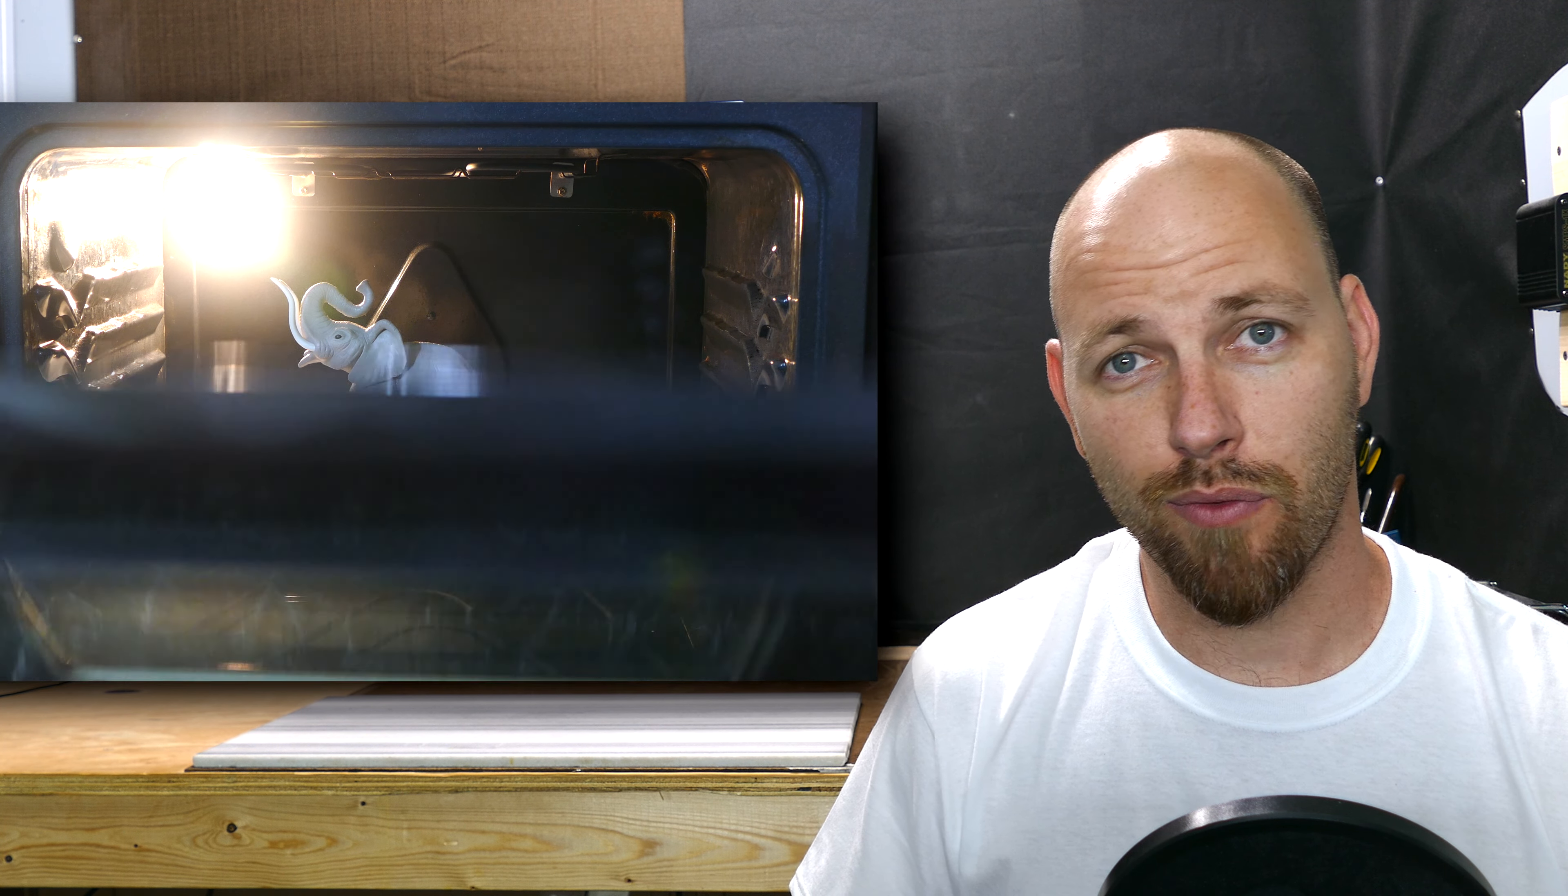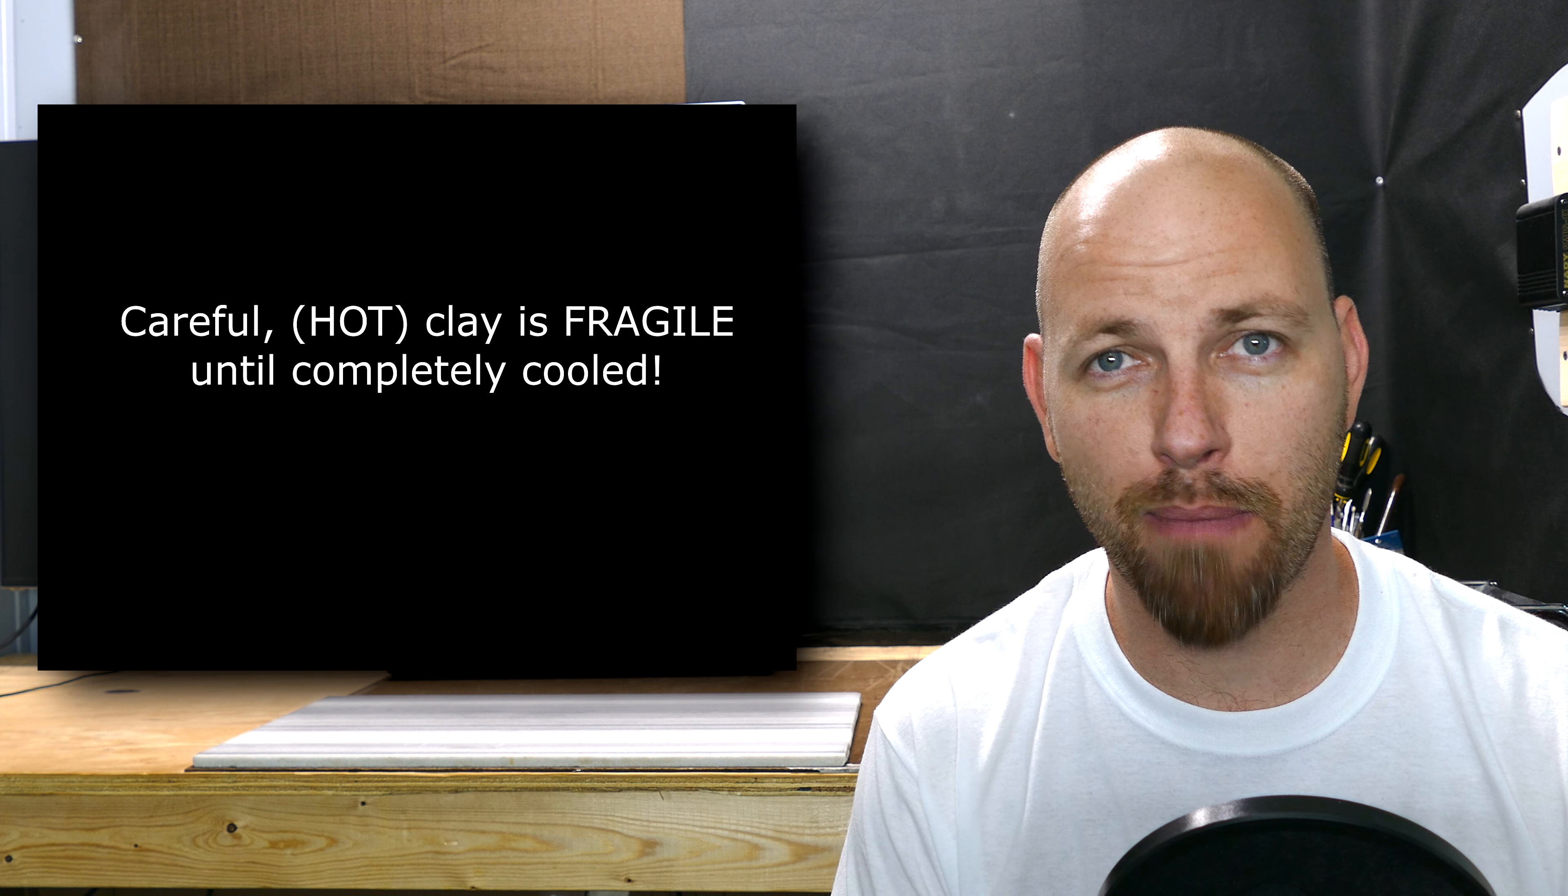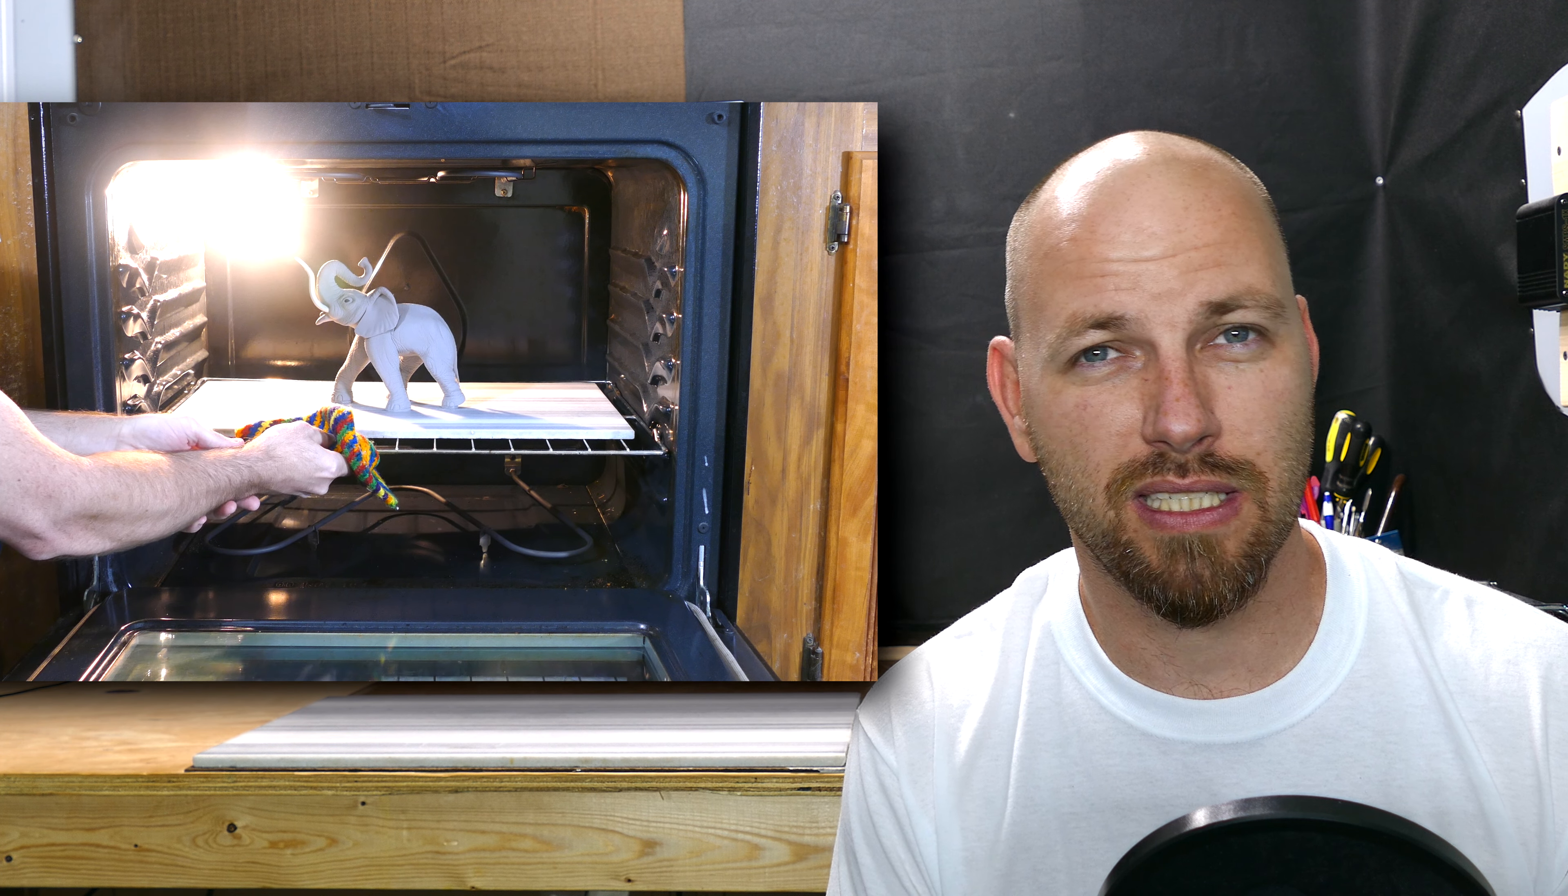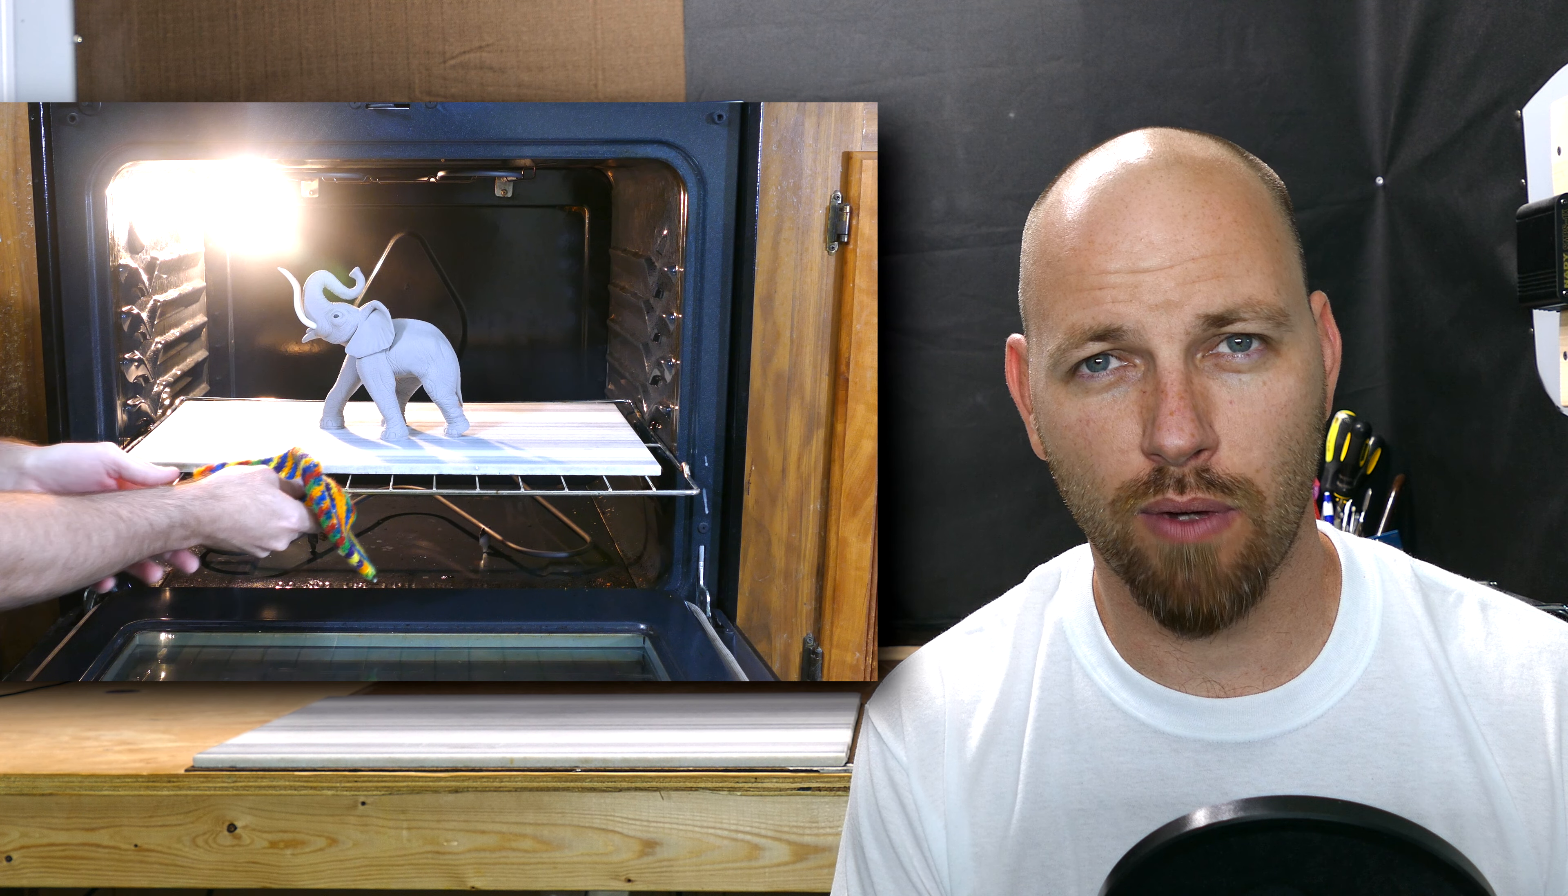When baking is complete, remove the item from the oven. Careful! It is now in its most fragile state that polymer clay ever is in, is when it first comes out of the oven when it's piping hot. It has no structural strength whatsoever. It doesn't gain its strength until it completely cools. It's brittle like soap bubbles. If you're not completely confident with removing the item from the oven without causing damage, just open the door all the way and partially slide the rack out like half way and let it cool sitting right there.